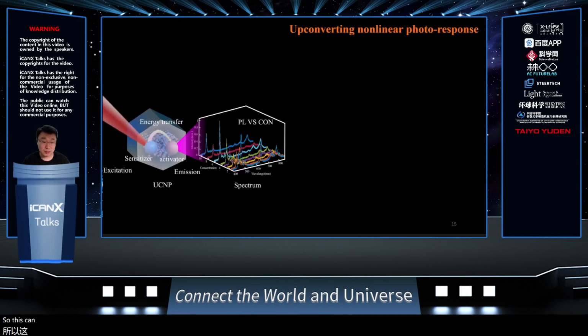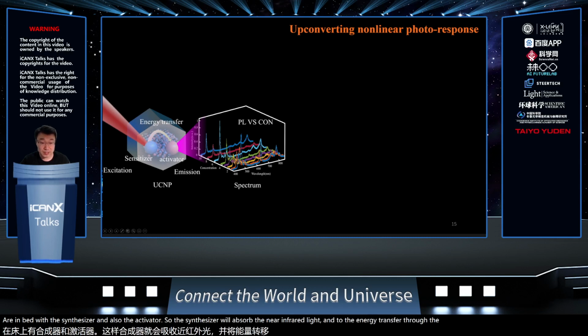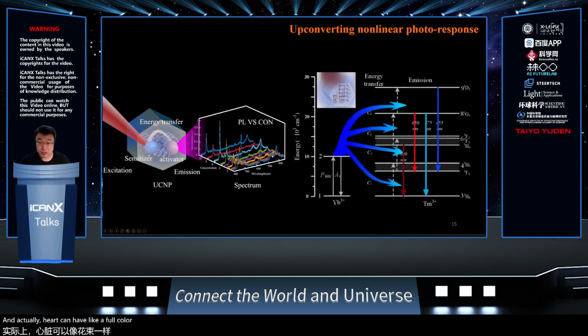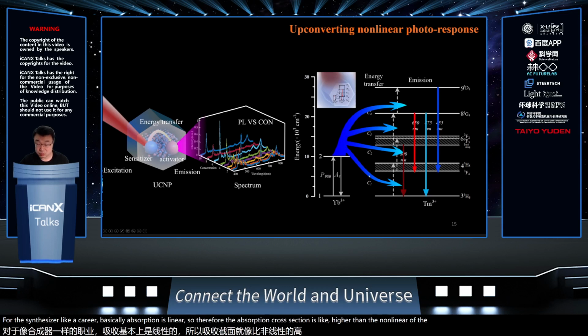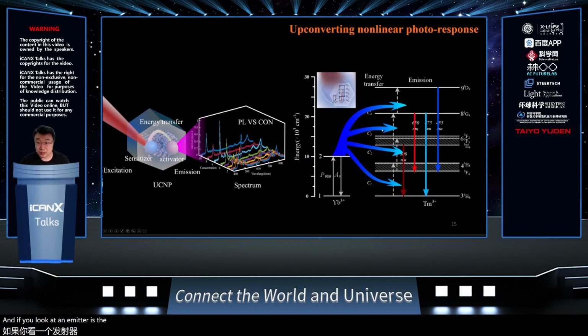This kind of nanoparticle is made of nanocrystals embedded with a sensitizer and also an activator. The sensitizer will absorb the near infrared light and do the energy transfer to the activator or the emitter to give you the emission, and actually can have a full color emission. If you look at the energy levels, it's quite interesting, because the absorption of the sensitizer, like ytterbium, is linear. So therefore, the absorption cross-section is higher than nonlinear absorption. And the emitter involves a nonlinear energy transfer.